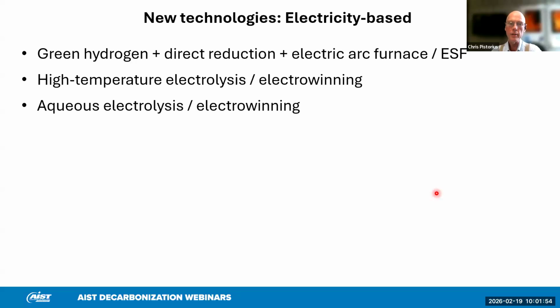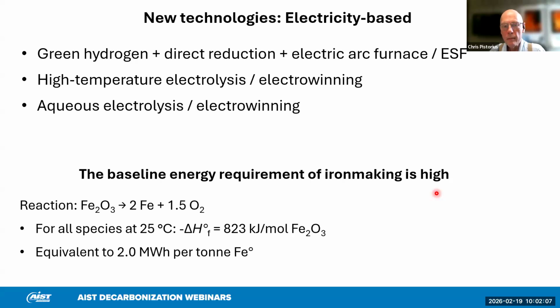And as context to this, just some numbers about how low we can expect the energy requirement to go for any of these processes. The important number here is the baseline number, which is what energy we need to break the bonds between iron and oxygen in our raw material, which is typically Fe2O3, or hematite. If you draw a boundary around the whole plant, you get hematite in, you get iron out, and you get oxygen as a byproduct. So this reaction is what is being done in all three of these electricity-based examples.